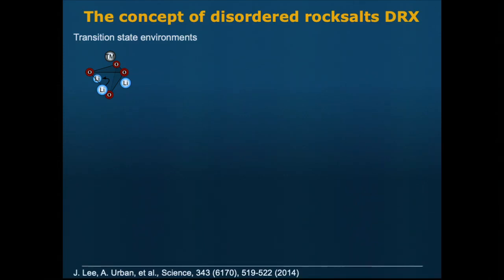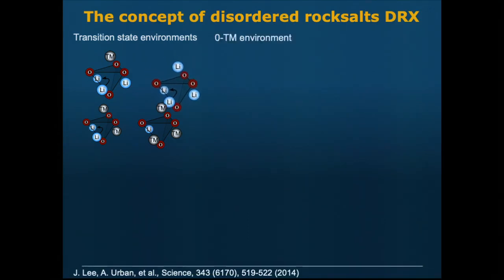What if you could change the transition state, right? If you just look at the different possible populations around the transition state, you could have more transition metal, but you could also have less. If you have enough lithium around, in principle, maybe you could make transition states with only lithium around them. And now you're in a better situation, right? Because when lithium diffuses in here, remember this one and this one would be vacant, it now only sees another 1 plus ion. So now you have a 1 plus ion seeing another 1 plus ion, so your electrostatics is going to be much less. So hopefully you will be much more tolerant to contraction of this tetrahedron, right?